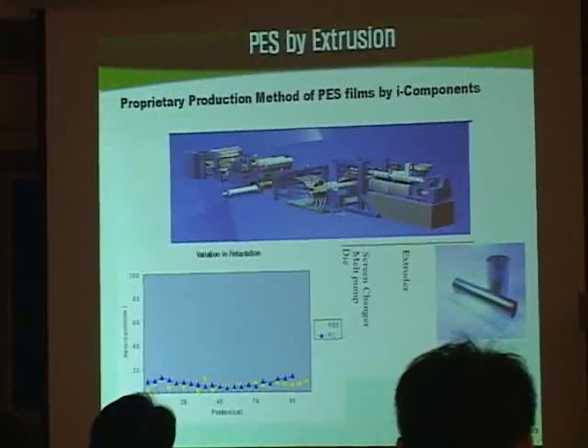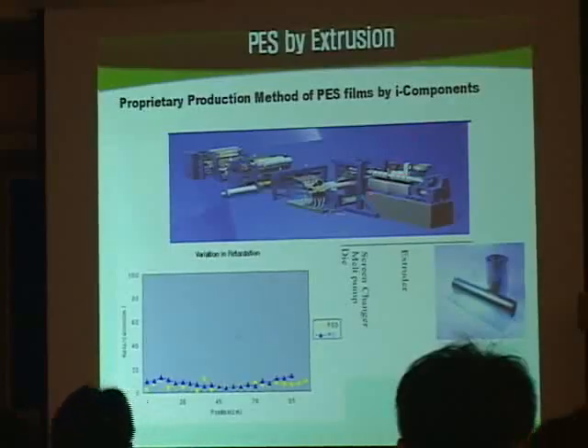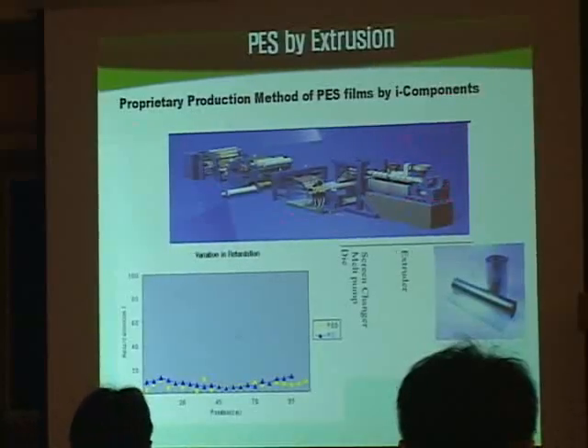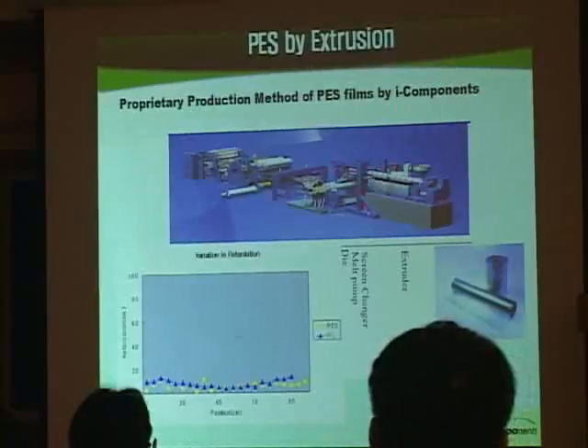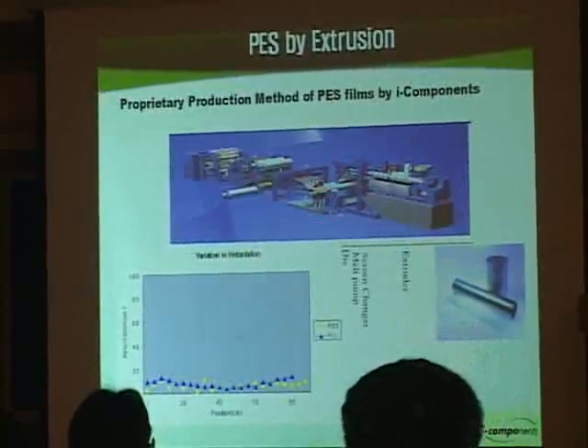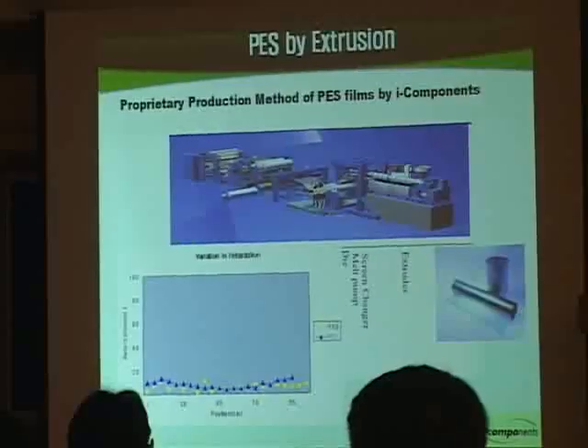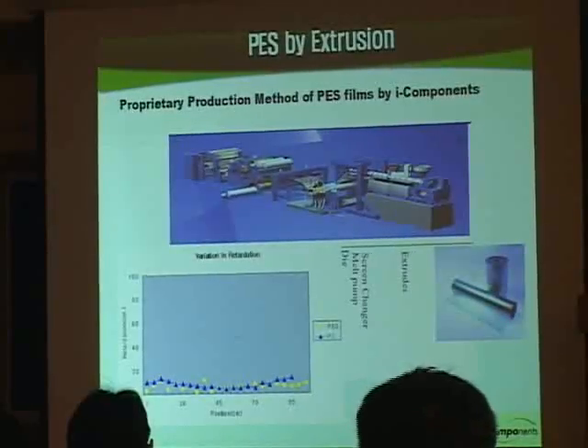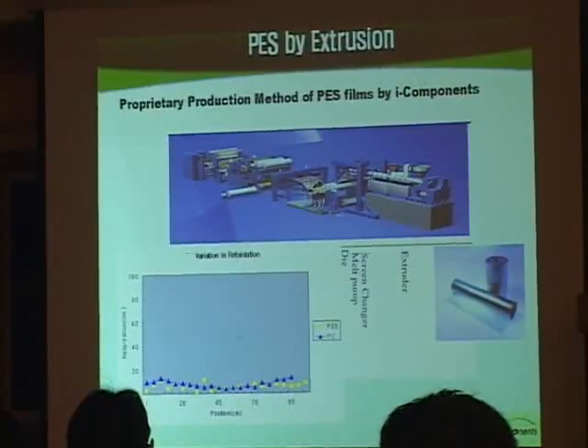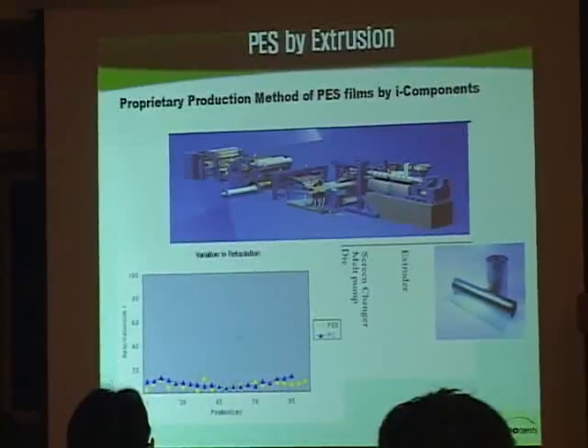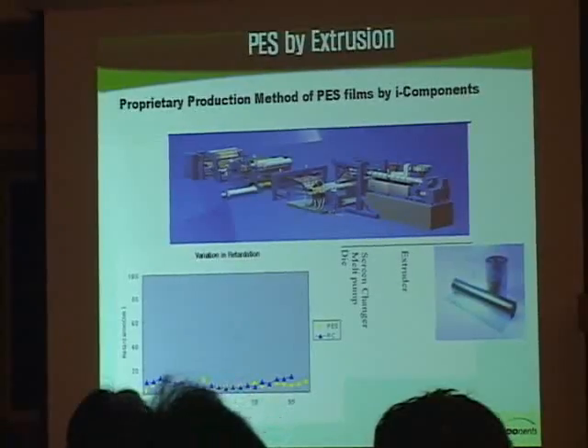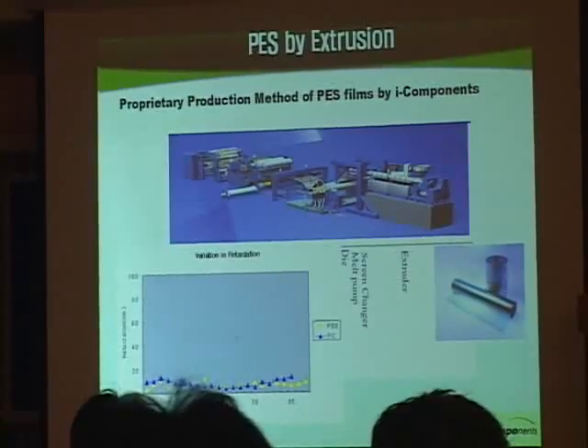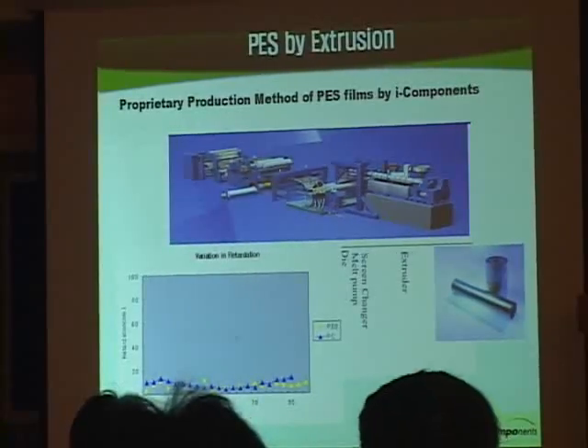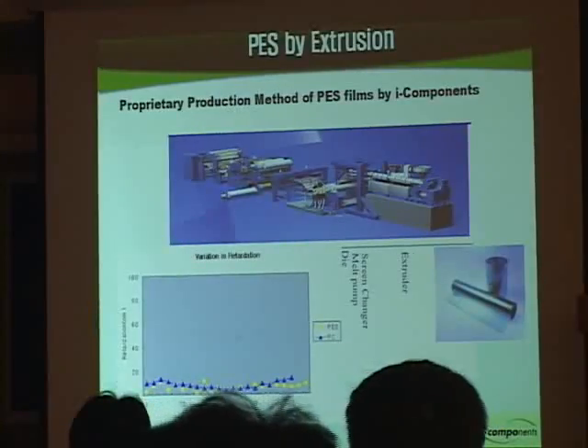At iComponent, we developed an extrusion process. This is a typical extrusion equipment. You have an extruder, and then use a die, and then calendar rolls, and then we do not use any drawing process. For PETs, you extrude it very thick, and then eventually draw to 6 to 8 times. So you have all kinds of draw axes in the film, but we didn't use a drawing process. But still, you are able to make the optical isotropy very good.